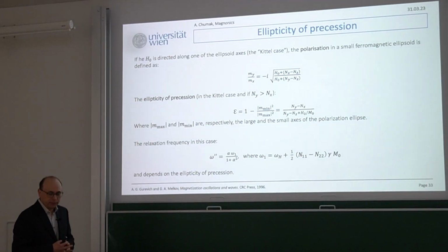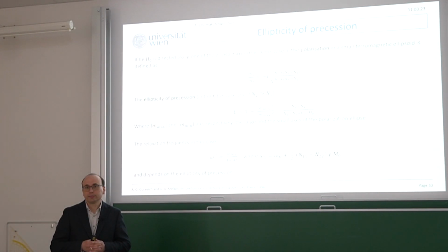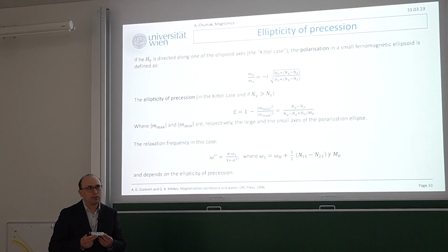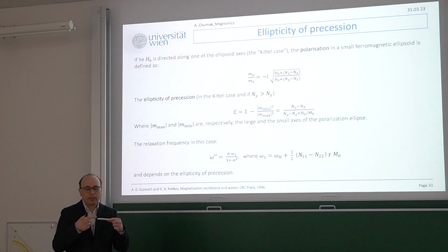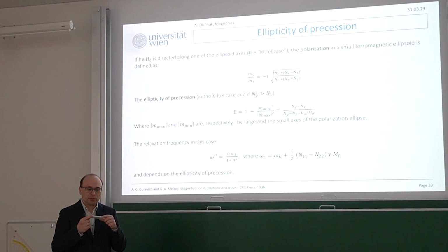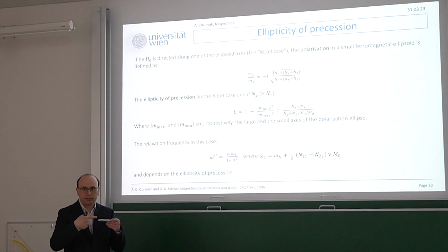Is there a rule of thumb for when we can consider the two surfaces to be infinitely separated? So when the component of the magnetization tends to 0, is it like in the millimeter range? It's all about the ratio, so you need to check the ratio. It's hard for me to give you some value, but let's say if my width or length is 1,000 times larger than the thickness, then I would already assume that we can ignore this demagnetization.